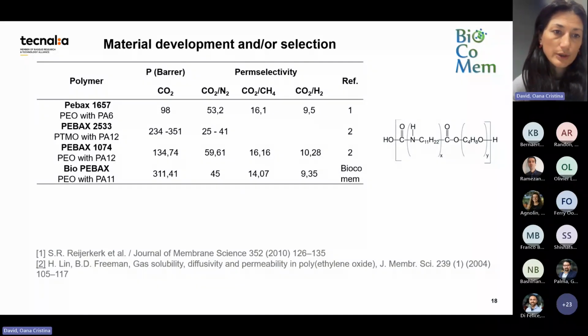Before we started the project, we had different PEBAs with their properties in terms of permeability for carbon dioxide. They are very good for carbon dioxide separation from nitrogen, and in comparison with polyimides, they are not so good for carbon dioxide separation from methane. It's also very interesting to highlight that they are reverse selective towards hydrogen. So carbon dioxide goes faster than hydrogen, even if hydrogen is smaller. And this is because of the high solubility of carbon dioxide in the polyethylene oxide part.